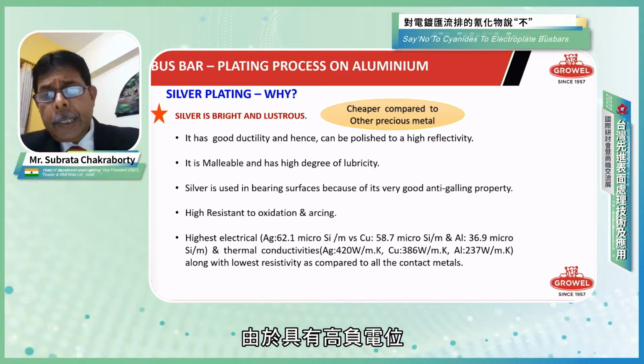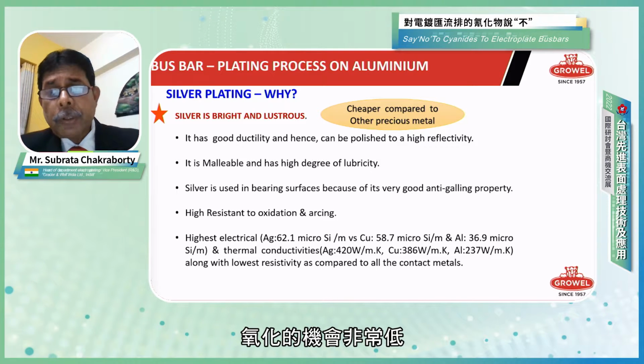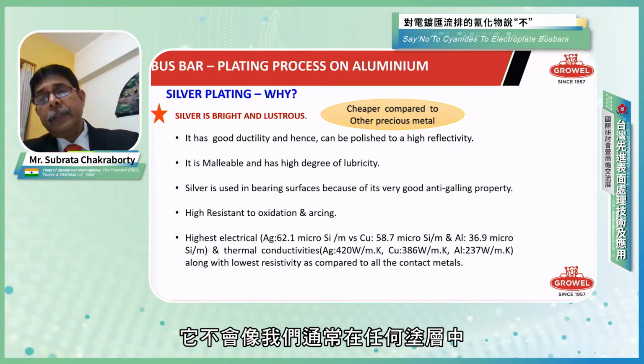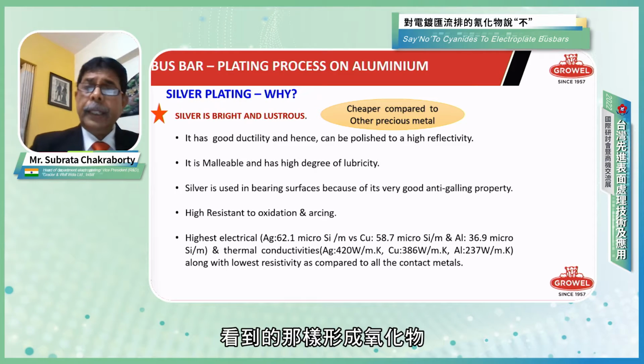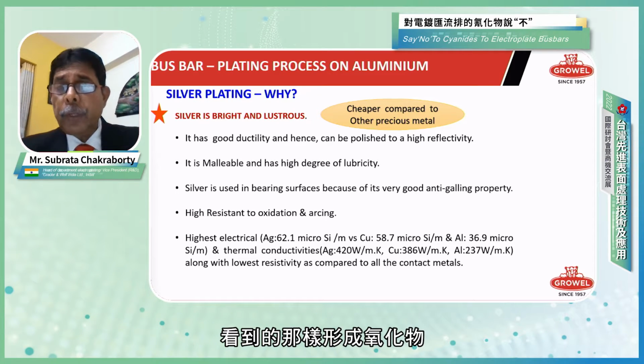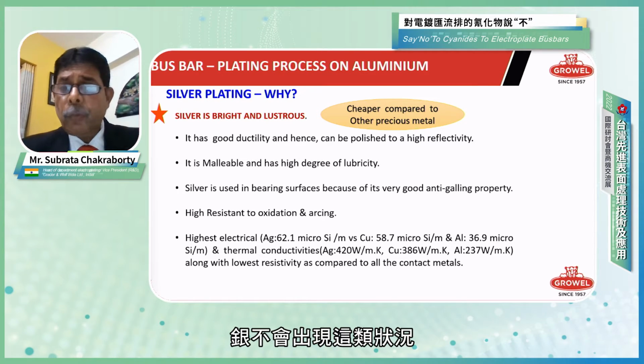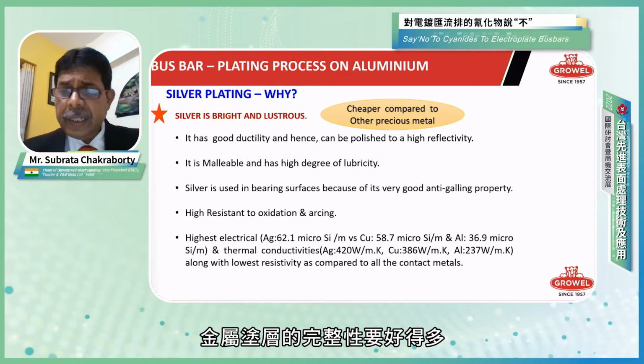Because of its high negative potential, the chance of oxidation is very, very low. So it doesn't form the oxide like we normally see for any coating like zinc on MS, where we get white rust and so on. Such a thing doesn't happen with silver, so the coating integrity is much better metallically.